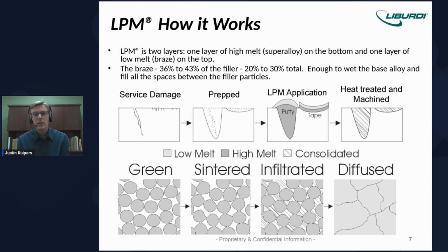Our first layer is the high melt constituent, which has a composition and melting point similar to the part that's being repaired. We then apply the braze constituent on top of that in a fixed ratio. The part then goes through a heat treatment, and after that, we end up with solid metal where our repair materials were applied, and then we machine or blend the part back to the original contour.